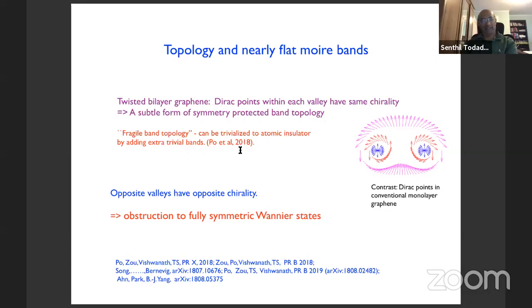This is a notion that has gotten some attention in the last 2 or 3 years, thanks to work by Adrian Po, Ashvin Vishwanath, Andrei Bernevig, and their collaborators. It turns out that the active bands of twisted bilayer graphene have that kind of band topology. Now, the opposite valleys, since they're related by time reversal, have opposite chirality. So this is a situation where there's an obstruction to fully symmetric Wannier states. Okay, so this situation is a bit subtle, it's a bit complicated.